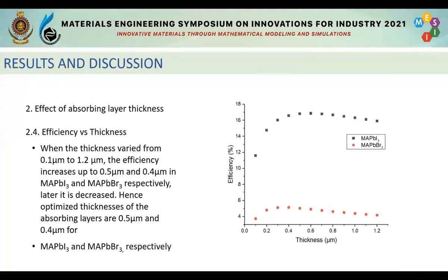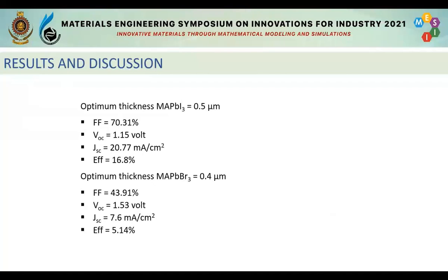This figure shows the efficiency versus thickness graph. When the thickness varied from 0.1 micrometer to 1.2 micrometer, the efficiency increases up to 0.5 micrometer and 0.4 micrometer in methylammonium lead iodide and methylammonium lead bromide respectively. Later it decreased. Hence, the optimized thicknesses of the absorbing layer are 0.5 micrometer and 0.4 micrometer for methylammonium lead iodide and methylammonium lead bromide respectively. These are the photovoltaic parameters for both methylammonium lead bromide and methylammonium lead iodide for optimal thicknesses.